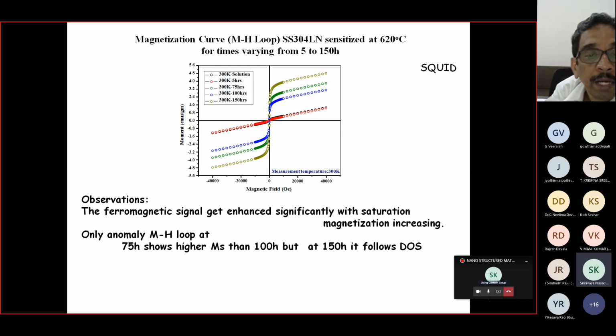Now, to further confirm the magnetic nature, we use what is known as SQUID. SQUID is also sort of a vibrating sample magnetometer only. Basically here, why it is called the SQUID is superconducting quantum interference device. In this, we can go to very low temperatures as well as very high magnetic fields also. From this particular, I think this might be a bit sort of confusing for my friends over here, but let me tell you that this is one magnetic technique where we are showing that this paramagnetic material is transforming to a ferromagnetic material, but intermediately there is an anomaly at 75 hours and 100 hours. If you remember the earlier one also, I showed that 75 hours it is showing a higher magnetization compared to the 100 hours.